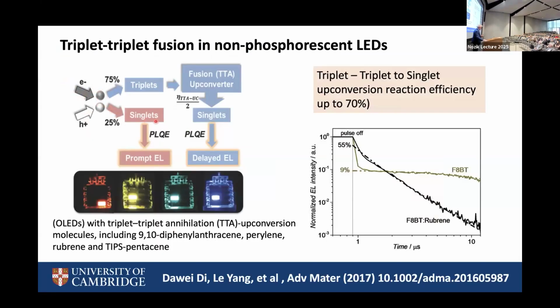This exciton, of course, will make singlets, which will give rapid luminescence. The 3/4 that make triplets, you can build up a high concentration of them to the point where the decay channel for triplets is that 2 triplets fuse, if they're in an overall spin state, to make a singlet. So we need 2 triplets, but we make 1 singlet because there is enough energy to do that. So we have a little sort of fusion converter.